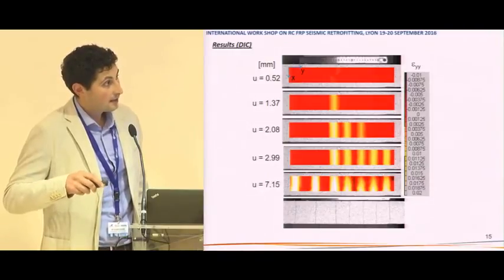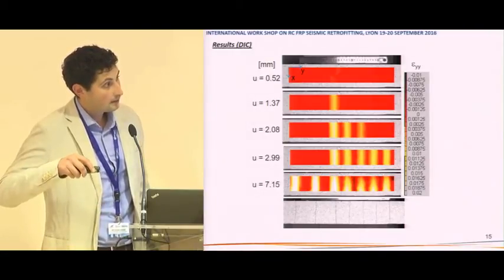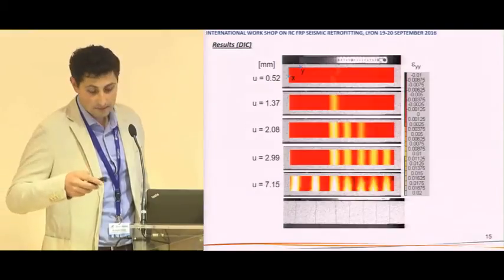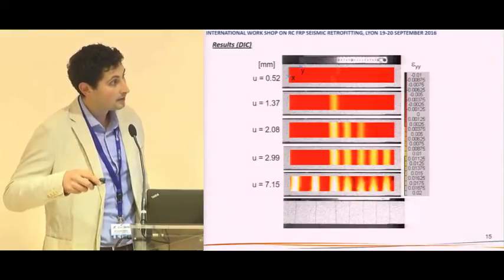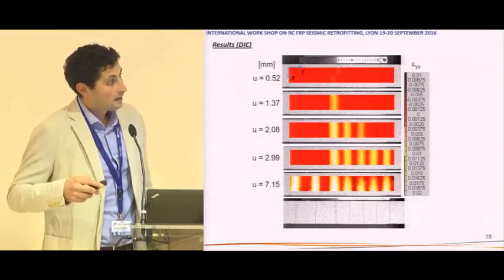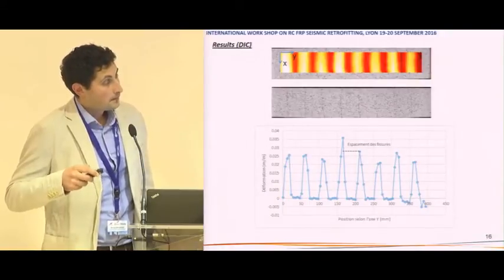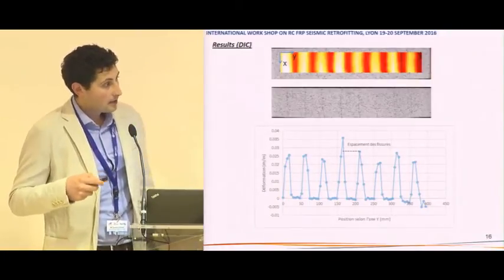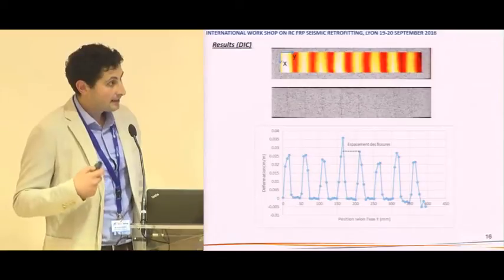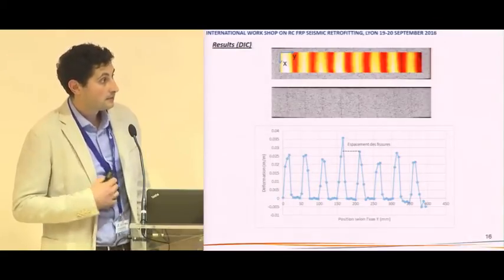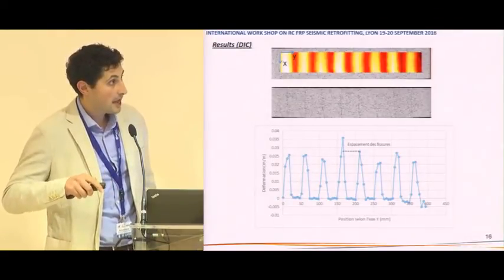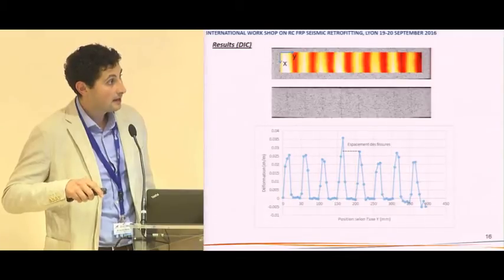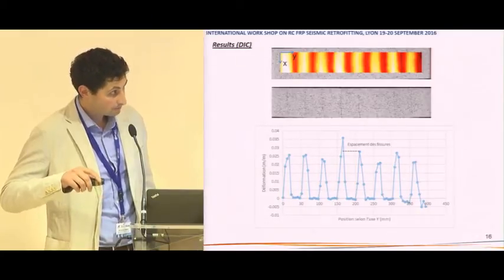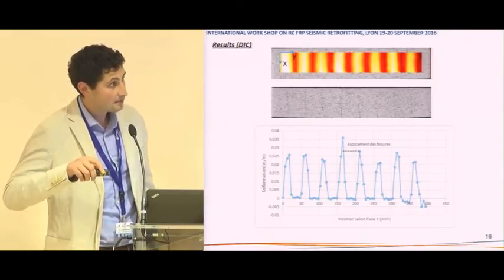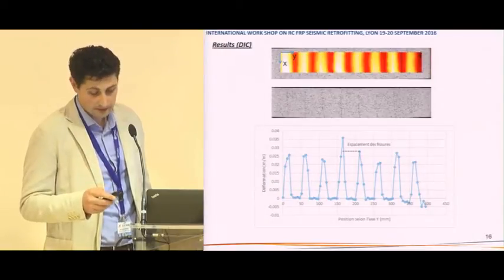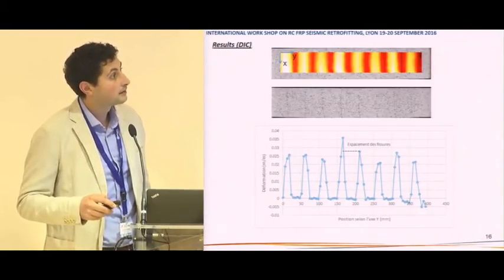Here you can see that the results obtained by correlation are coherent with reality. The use of digital image correlation permits us to deeply characterize the behavior of the composite, because it permits us to obtain the strain between the cracks and exactly the distance between each one of the cracks.